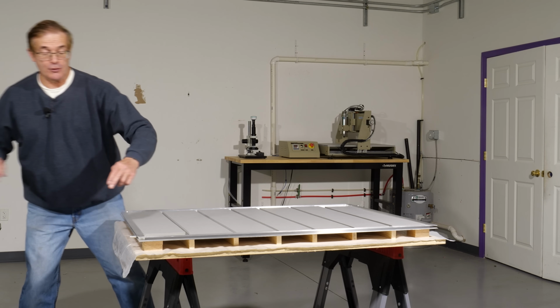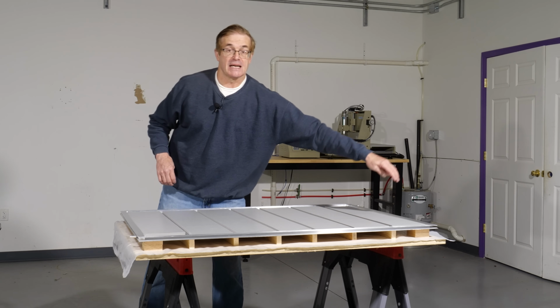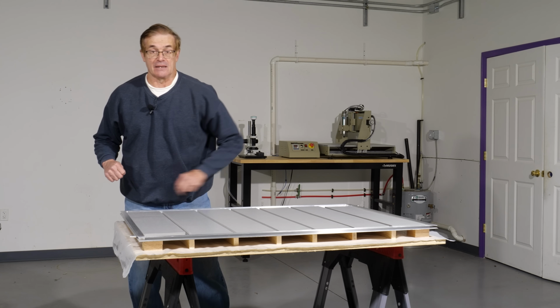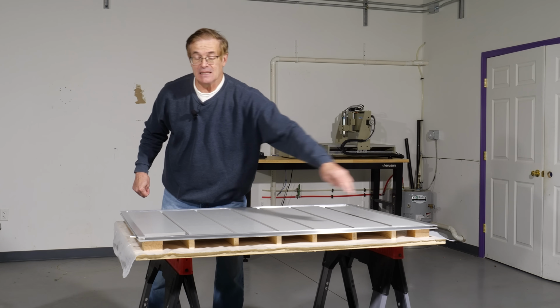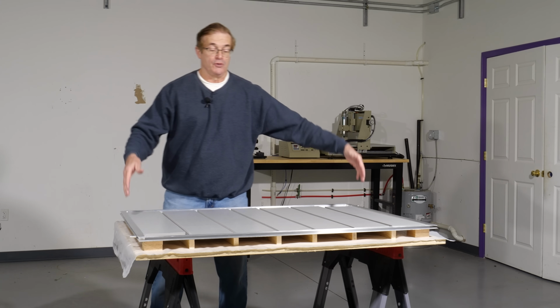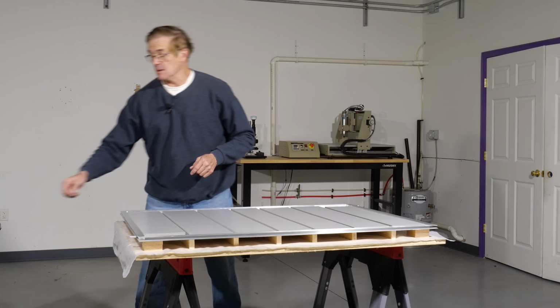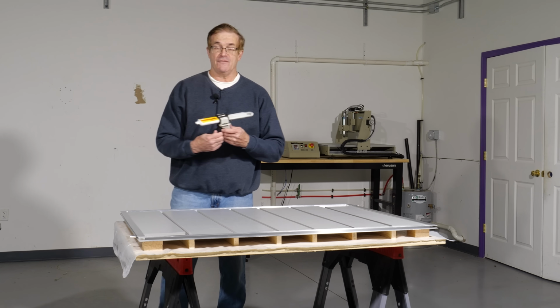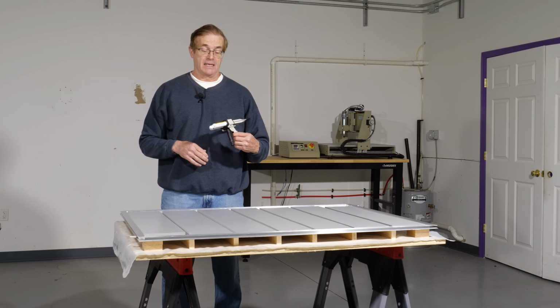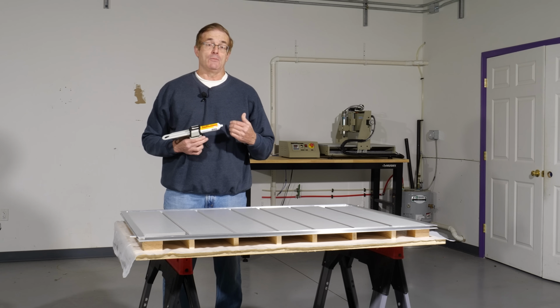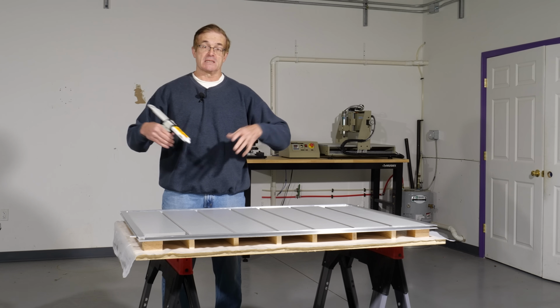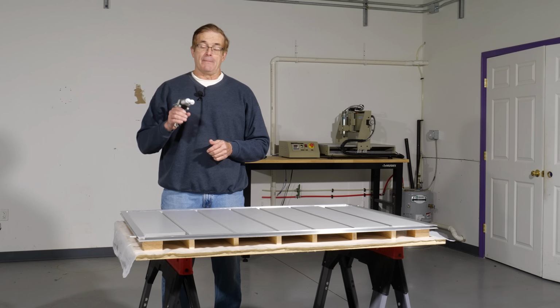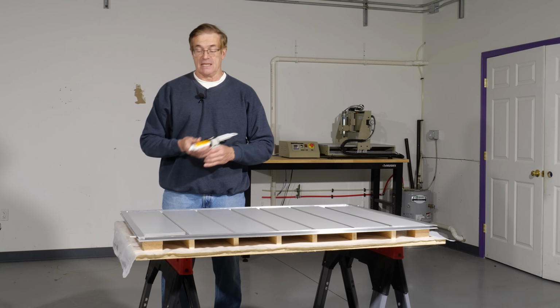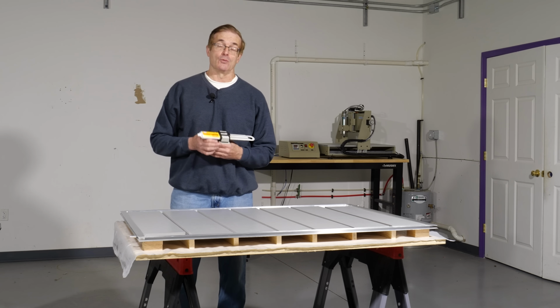So after thoroughly cleaning off the contact points, then sanding them, and then cleaning them off again, we've got the whole thing mounted on a table, and I'm going to use some of this toughened epoxy from Loctite. It's good stuff. It's a lot more expensive per gram than if you mixed up a bucket of this yourself. But in these syringes, they're very nice and neat and easy to work with.